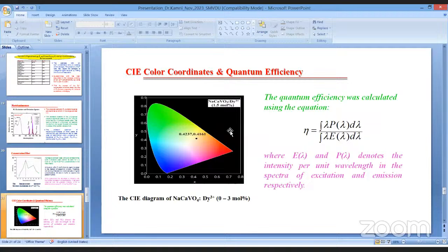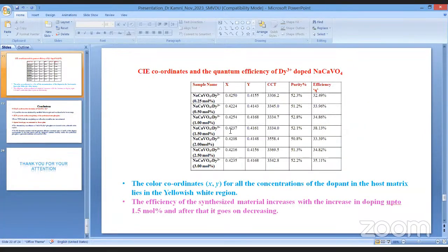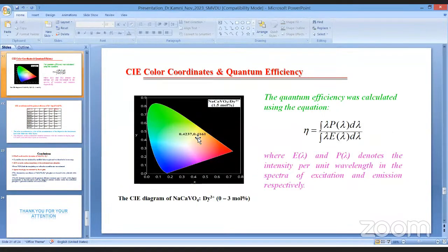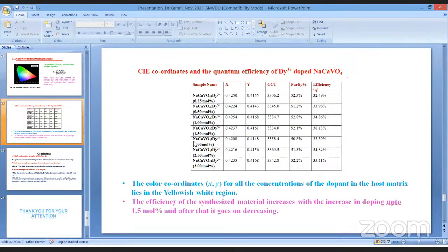And this is the CIE color coordinates and quantum efficiency. The quantum efficiency was calculated using this equation, where E lambda and P lambda denote the intensity per unit wavelength in the spectra of excitation and emission respectively. Here we have calculated the color purity and the efficiency for each synthesized sample. The color coordinates for all the concentrations of the dopant in the host matrix lie in the yellowish white region, as you can see here in this picture also. The efficiency of the synthesized material increases with the increase in the doping up to 1.5 mole%, and after that it goes on decreasing.